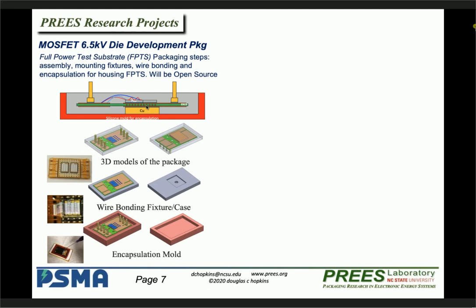For instance, we might use a soft solder, but we can go ahead and simulate with sintered silver. We would have done sintered silver, except of course the virus kept us out of the lab. If you use sintered silver, we know what the process is, we know what the characteristics are, we can model all that and say, okay, this is the performance we see using the soft solder that we produce. But again, we're looking more at the electrical and thermal performance and not necessarily the long-term mechanical performance. We do want to show the comparisons between, for instance, using ceramics and getting into organics, going from polyimides down into epoxies, et cetera, and show the mechanical aspects of it also.